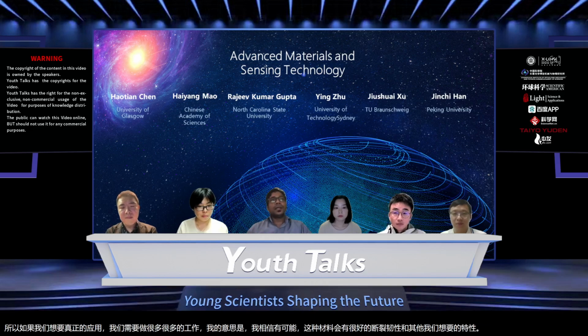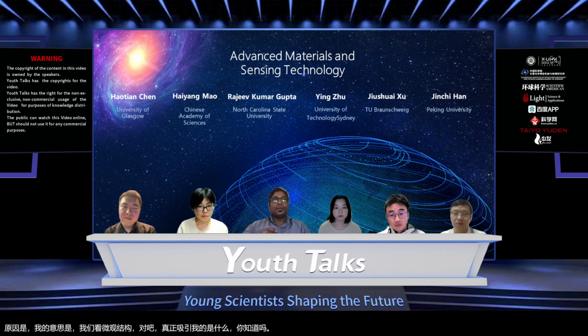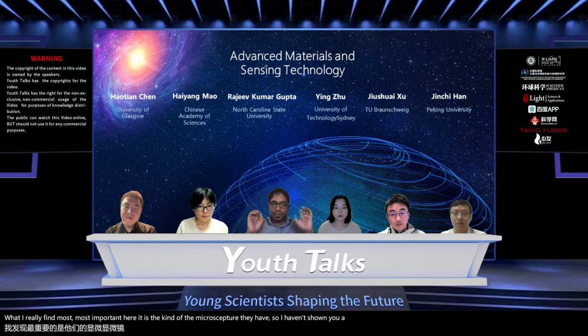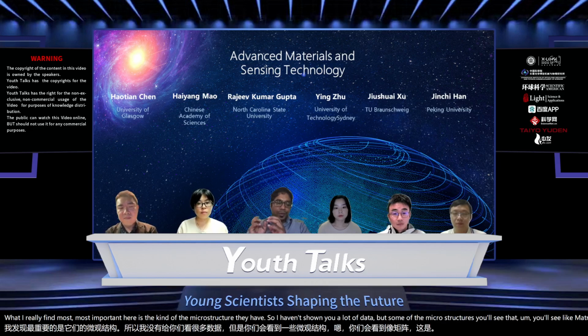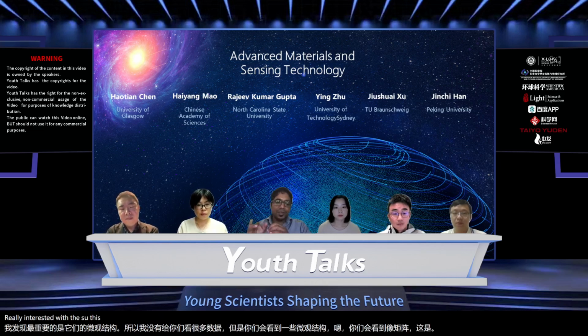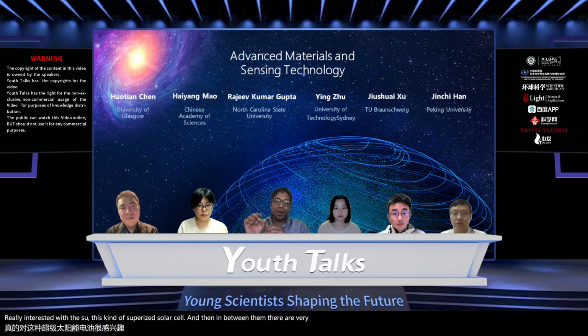And the reason is that, if you look at the microstructure, what is really fascinating to me, or what I find most important here, is the microstructure they have. I haven't shown you a lot of data, but in some of the microstructures you will see a matrix which is really enriched with the solute. It's kind of a supersaturated solid solution. And then in between them, there are very small pockets of really soft aluminum, which is not enriched with any